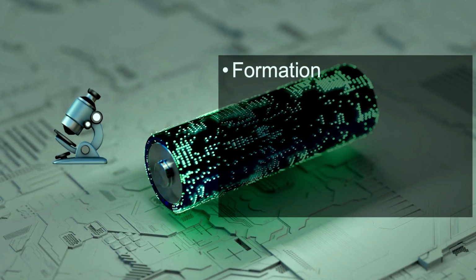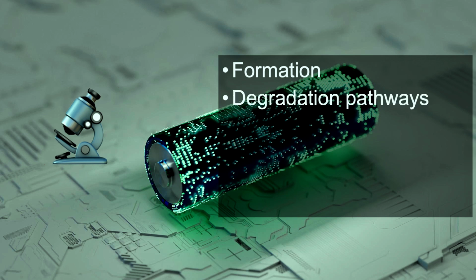So there's our microscope. I'm interested in studying things like formation. This is when you first take a battery and you charge it up and discharge it for the first time. It turns out that the way that you do this has really profound long-term implications for the cycle life of the battery. And it's really not well understood, even in lithium-ion batteries, why this is the case. It's also a massive bottleneck in terms of production. It takes days. I'm interested in degradation pathways.